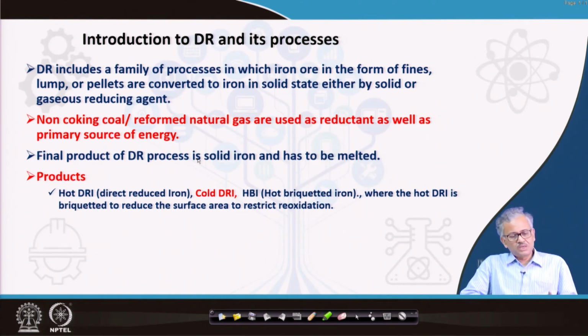That is why its products are hot DRI, cold DRI, and HBI, hot briquetted iron. In hot briquetted iron, the hot DRI is briquetted into a bigger shape. If you do the hot briquetting, you are decreasing the surface area, so its propensity for reoxidation will decrease to some extent, because the DRI is very porous. If you briquetize it, on the surface you reduce some amount of pores. Besides, the briquettes' melting efficiency is sometimes also better. So these are the three products: hot DRI, cold DRI, and hot briquetted iron.